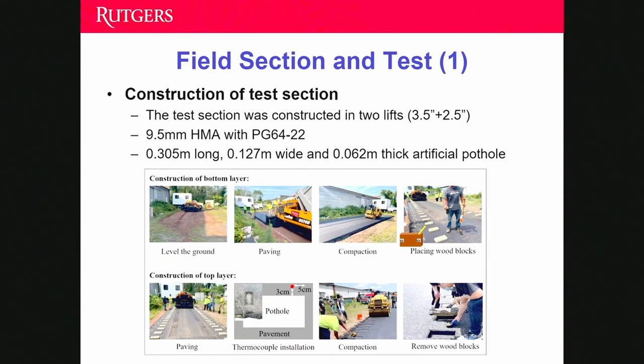So basically, after paving the bottom layer, we put some wood blocks on it, and then we directly paved the top layer. And after paving, we removed the wood blocks immediately. And after cooling down, we have these artificial potholes. And each pothole was around 30 centimeter long, 13 centimeter wide, and 6.2 centimeter thick.